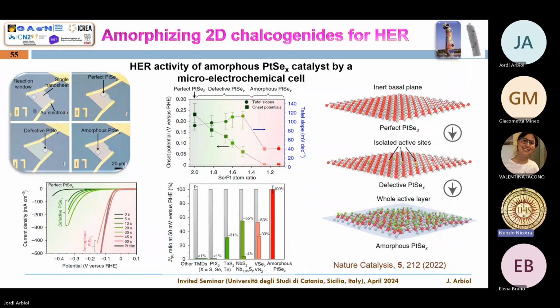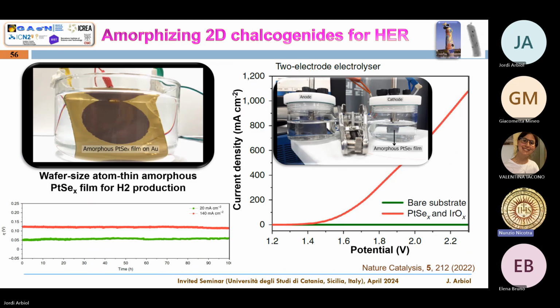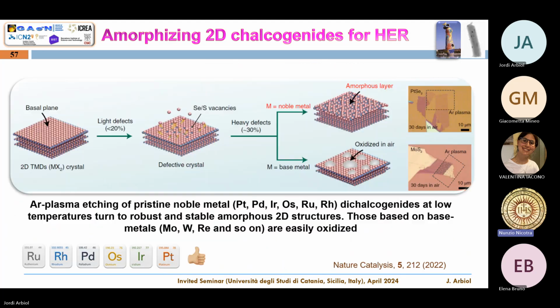And at the end, if you compare with the Tafel slope and everything, you see that the best numbers, the minimum numbers for the Tafel slope, for example, and the onset potential, the minimum ones, are for the ones that are perfectly amorphized. And the comparison with a perfect platinum, it's exactly the same. It works as a perfect platinum foil. Okay, so without expending so much platinum, because at the end it's a single layer.